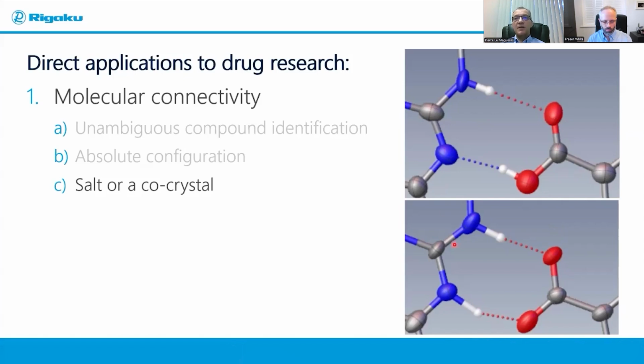However, the same two molecules could also crystallize as a salt. You see here that this hydrogen atom that I'm circling with my cursor is now linked to the nitrogen instead of being linked to the oxygen like on the top picture. So as a result, the left-hand side molecule now bears a plus charge, whereas the right-hand side molecule bears a minus charge. We have a co-crystallization of a cation with an anion, and therefore this is a salt. And sure enough, these two crystal structures had a different arrangement in the crystal. And that could only be obtained also via getting the crystal structure.